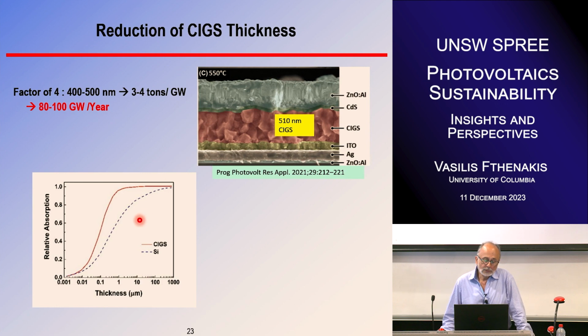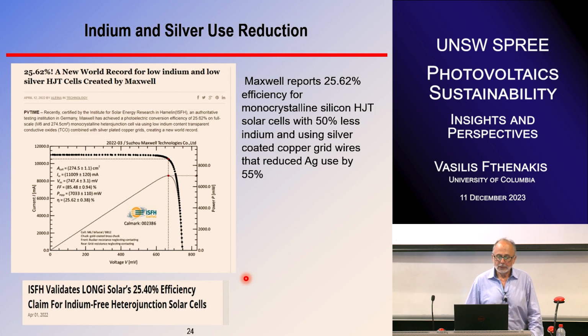And the optical efficiency of this material is very high. So you can get down to a fraction of a micron, and it has been done in the lab. So this is how the industry is looking at the supply and the demand to get into thinner layers. Also, in the lab there are prototypes that use less indium and less silver together. For example, Maxwell reported 25.6% efficiency for a monocrystalline silicon heterojunction, using 50% less indium than the conventional technology, and using a lot less silver by just having copper grid wires that reduce silver.